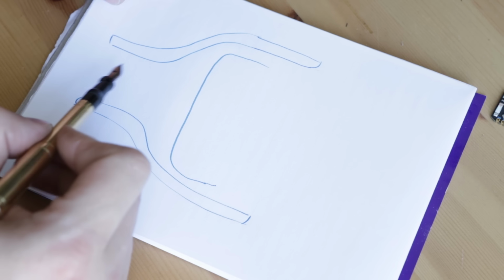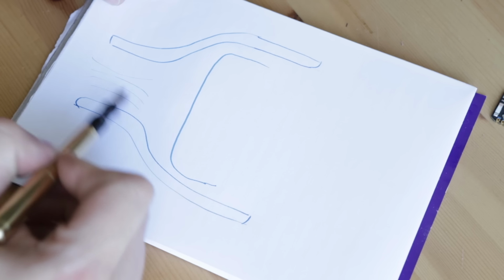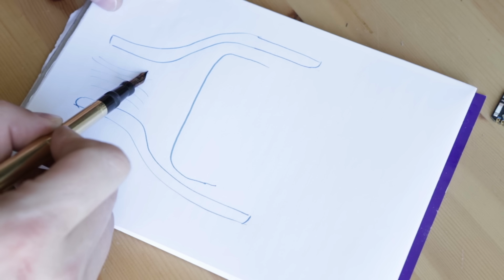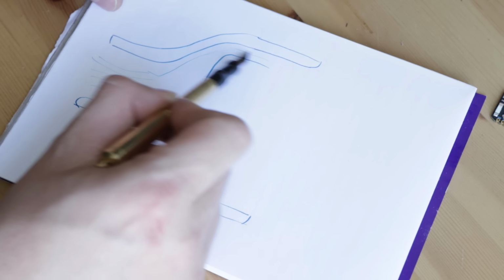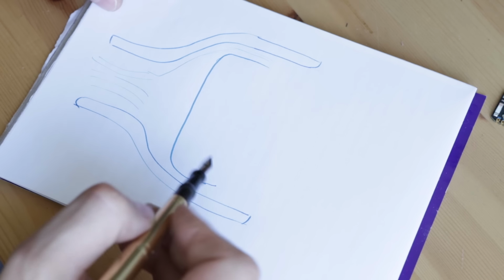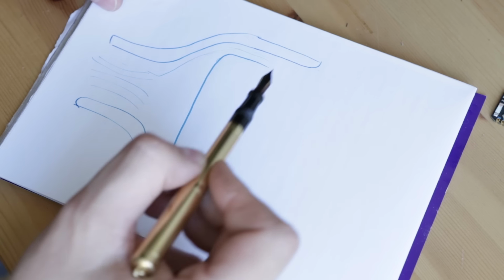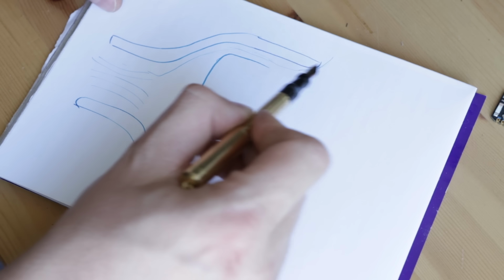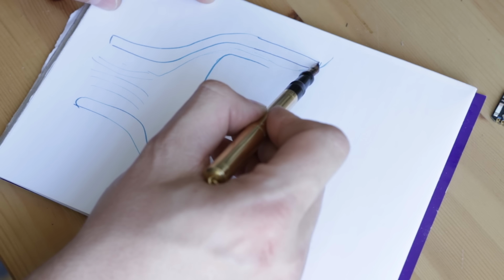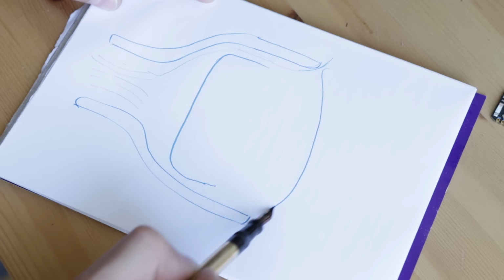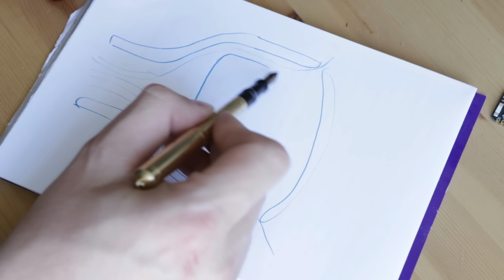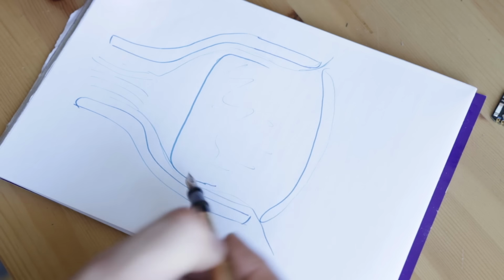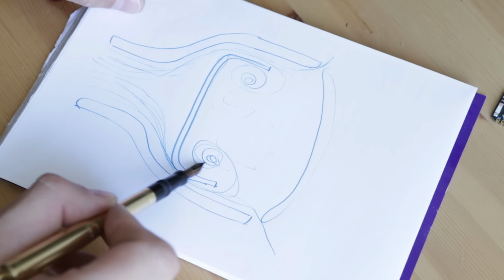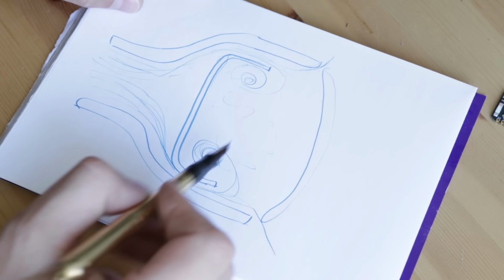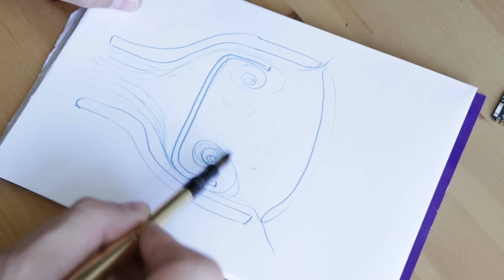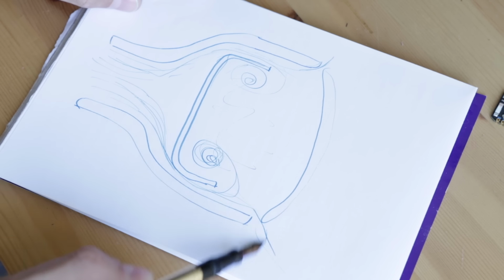Another possible problem is that when we are flowing the purging gas from the back, it actually has to go between the glass and the anode cup, because the anode cup is a solid piece of metal, so it needs to go this way, and then it escapes here in the gap between the edge of the envelope and the front glass. And we are hoping that the gas from the back will displace also the gas in the front between the digits. But the reality might be that the gas is just going like this and whirling here and still leaving some air here, because it's not possible to get it through this gap.